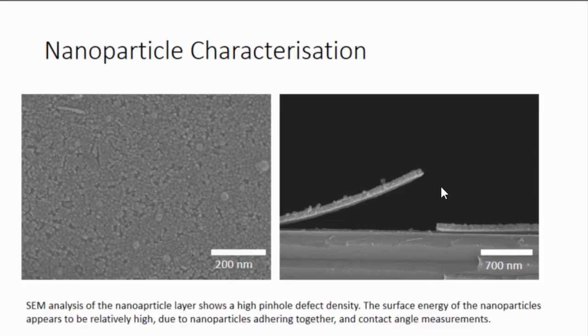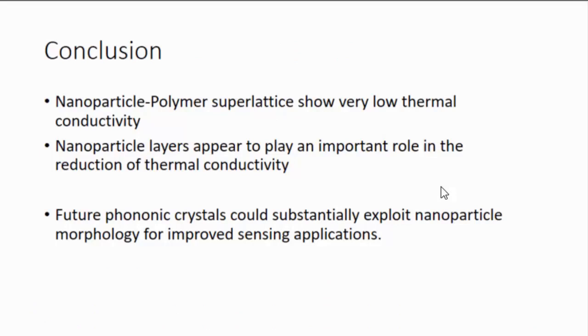So essentially, what are my conclusions from this? It seems that our nanoparticle polymer superlattices have a really strong reduction in thermal conductivity with respect to bulk. It's been between 1 and 2 orders of magnitude with respect to the polymer and the bulk silicon dioxide. And it appears that the nanoparticles in particular, based on other work and modelling, seem to be a key player in all of this. So if we're attempting to maximise the phononic bandgap in future, I think it's really worth investigating and pushing forward with the nanoparticle morphology in particular.